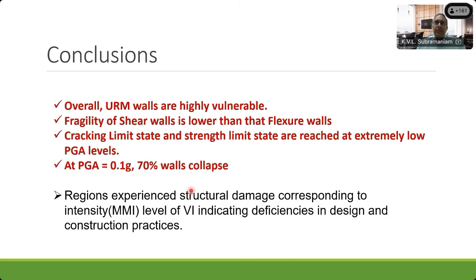Its stiffness, its Young's modulus, is very low compared to mortar. While its strength is moderate to high, its modulus is very, very soft. And what that does is it completely changes the stress state in the masonry compared to what we are expected to believe when you're dealing with high stiffness bricks in masonry. What we find going further is, if we consider bringing in the variabilities, we find that different parameters of the material model influence the behavior of walls differently.